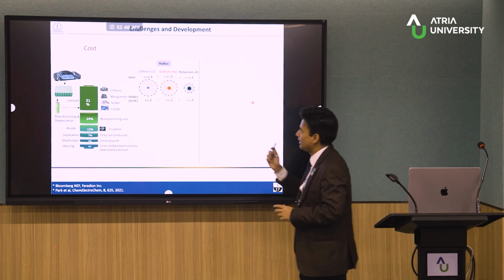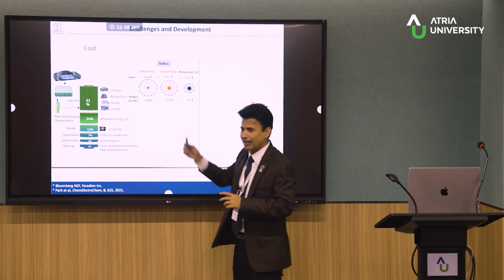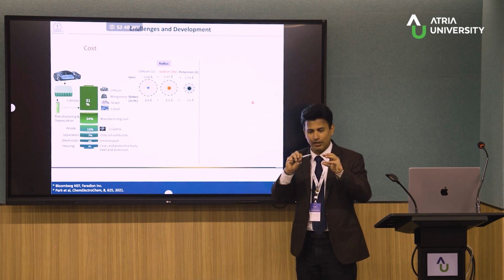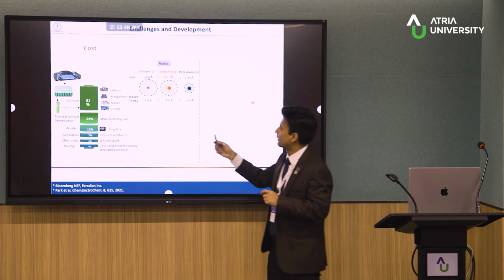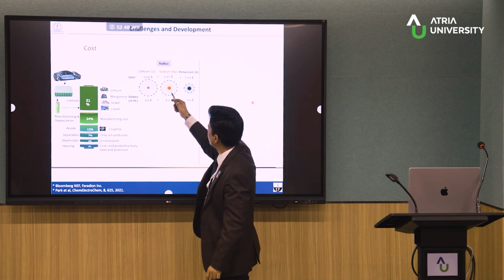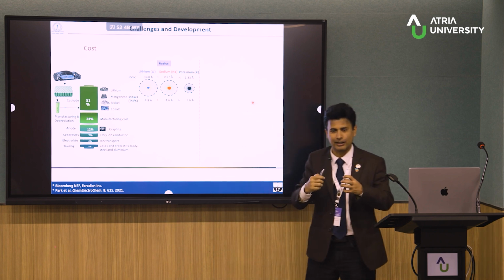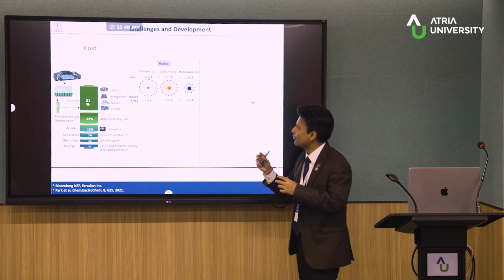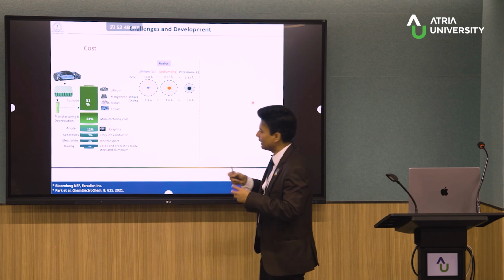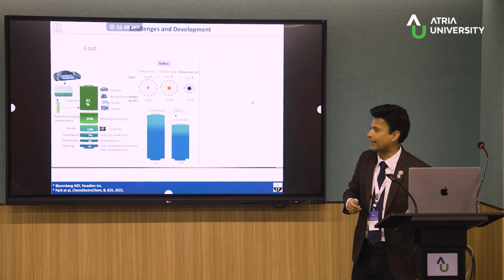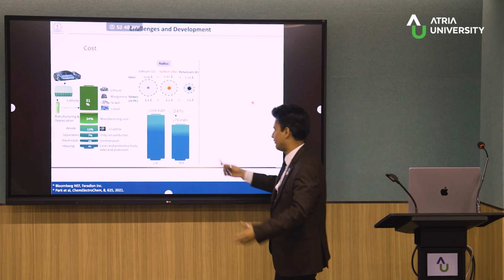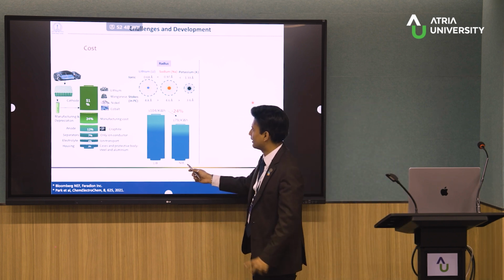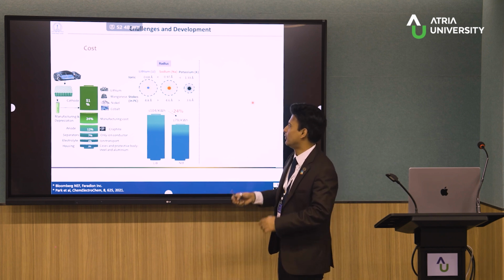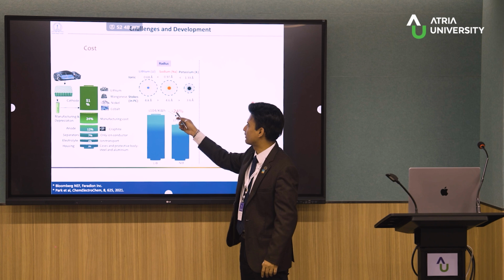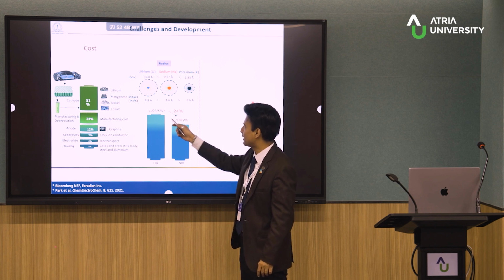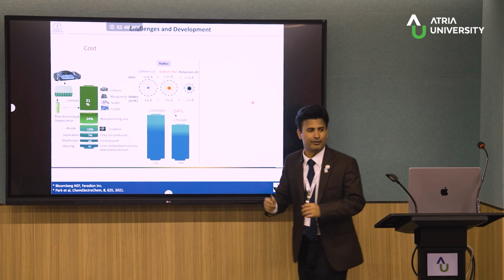Now, when we talk about lithium, sodium, and potassium, granted the size of lithium is small. Sodium is bigger, potassium is bigger, but if we see the solvation sphere, the Stokes radius, for sodium and potassium, because of the high electropositivity, it can be smaller. As a result, the Stokes radius can be small, and they can also intercalate nicely. And this is typically the lithium-ion battery and sodium-ion battery. Because the sodium voltage is low, there is some minus 20% less energy density, but the cost per kilowatt hour can be very, very good.